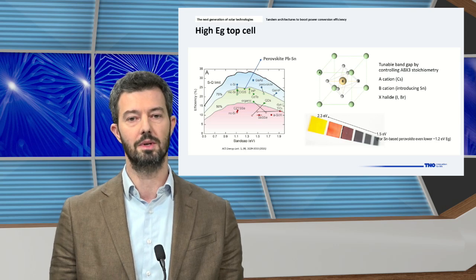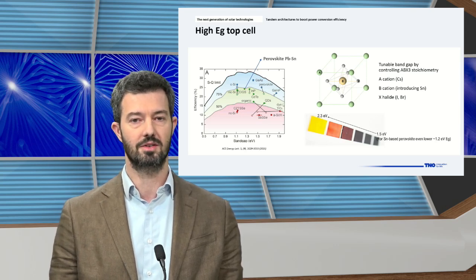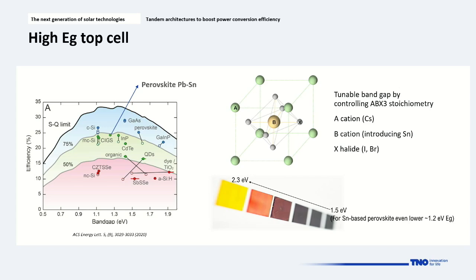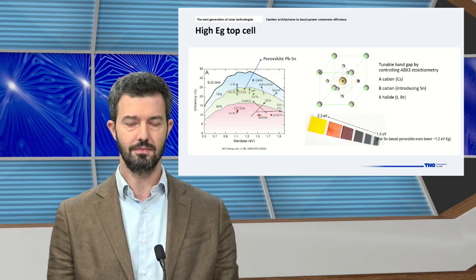We can easily tune the stoichiometry of this ABX3 structure by changing a little bit the cation and the halides, for instance, and we can change a little bit the absorption edge, so in which part of the spectrum the material will absorb. The second reason is that when you do this trick, you can still get very high numbers in terms of power conversion efficiency. And this range of band gap is the most suited to be complementary with existing commercially available technology like silicon, or other thin film technology like CIGS.